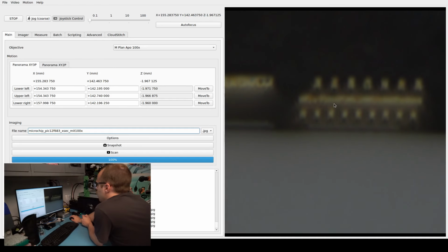Zooming in a little closer, we can again see the 3 metal layers, and barely at the limits of optical microscopy, there is a slight angle visible on some of the tracks where the wires are a little bit wider at the bottom than the top. This is characteristic of RIE etched aluminum.